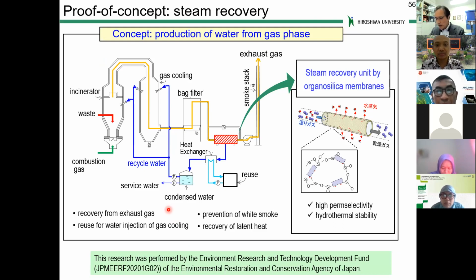Now, this type of membrane is under proof of concept experiment for steam recovery. The concept is production of water from the gas phase. Here we have the typical incinerator. Waste is combusted with air in this incinerator, and then the exhausted gas should be cooled down, sometimes with injection of liquid water to cool down this gas, and then usually exhausted from the smoke stack. So we propose the use of membranes in the process to recover steam. Recovered steam is then re-injected for gas cooling.